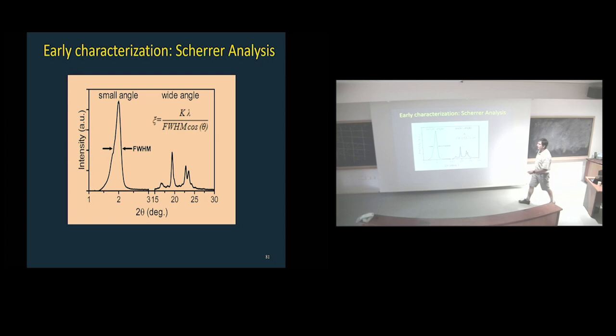What else were we doing? We started learning to use carefully the width of the peaks in an X-ray diffraction, at as low Q as possible, to not have instrumental broadening, et cetera, et cetera. And what do we do with a full width half maximum? You can derive a Scherrer width. You use a Scherrer model to derive a domain size. So you saw all those crystals, and domain sizes are like 20 nanometers. It's like, what? 20 nanometers, and 100 micron crystals on the microscope? What the hell's happening? And remember, this is the 001 reflection, so you're looking in the direction of 001. So you're looking at the lamella, right? How many lamellas are there in a domain? That's what that means. That's what we discovered.